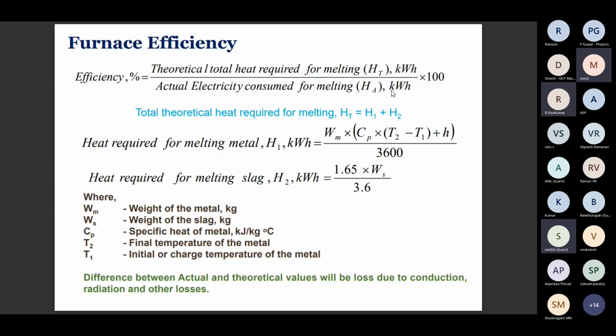So this is the formula used for calculating the furnace efficiency. Basically, the furnace efficiency is less than 70% only. How to calculate? The efficiency formula is theoretical total heat required divided by actual electricity consumed for melting. We know the theoretical heat requirement is almost 392 kWh per tonne. The actual electricity consumed for melting is calculated in two ways. One is heat required for melting the metal, and the other is heat required for melting the slag, that is H1 and H2. So Wm into Cp into (T2 minus T1) plus H, the latent heat, divided by 3600. 3600 is the kilojoules to kWh conversion.